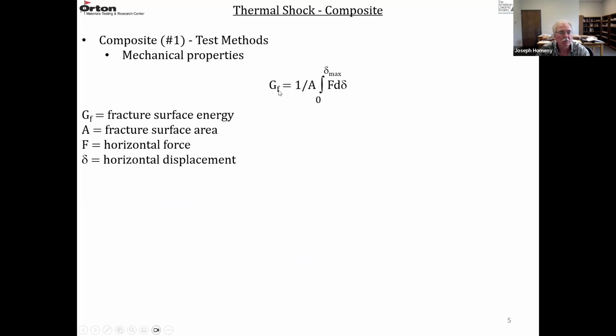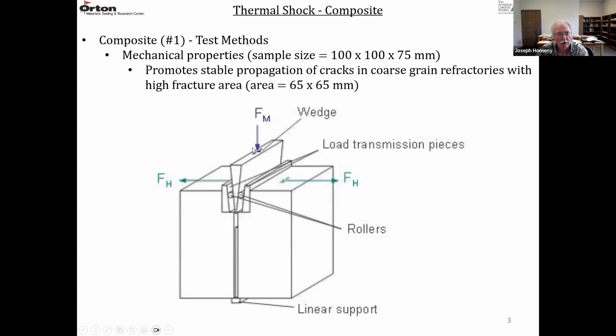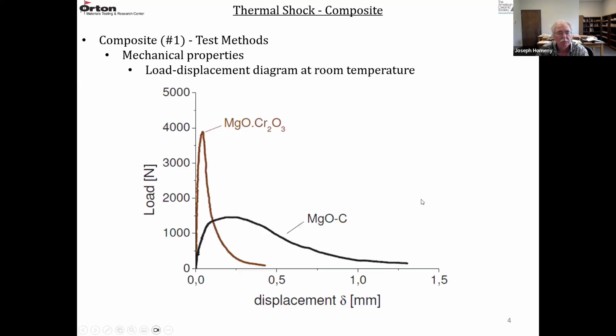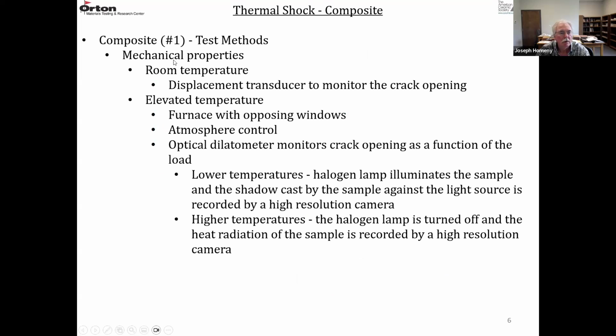Again, this formula for the fracture surface energy, GF, is just 1 over the area, and it's the integral over the force displacement curve, F dδ. F is the horizontal force, δ is the horizontal displacement. At room temperature, to get the horizontal displacement, you just use a displacement transducer that monitors the crack opening. Obviously, you can't do that at high temperatures because the transducer is not suitable for use at high temperatures.